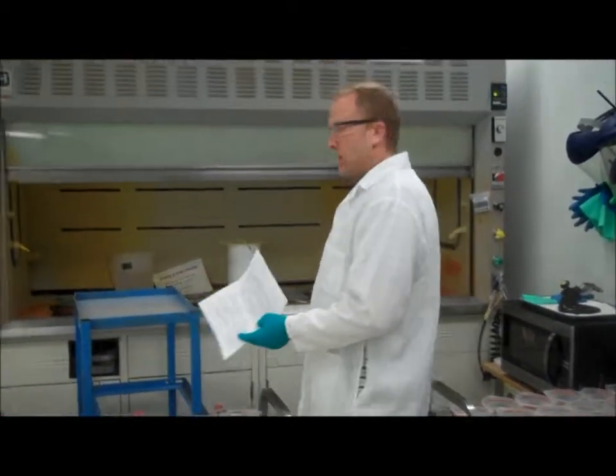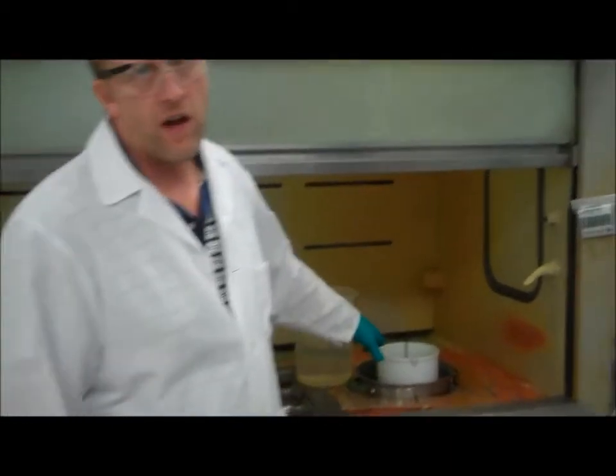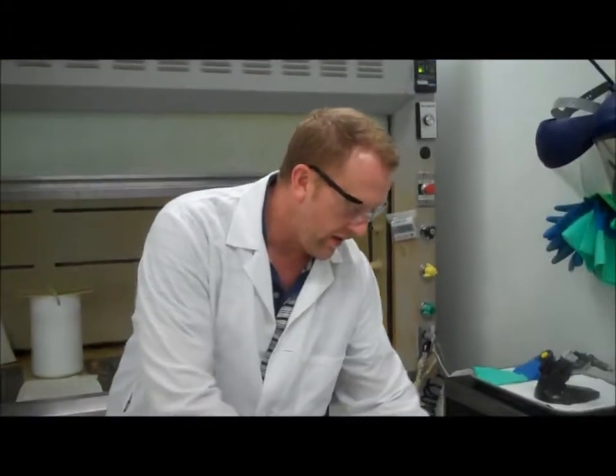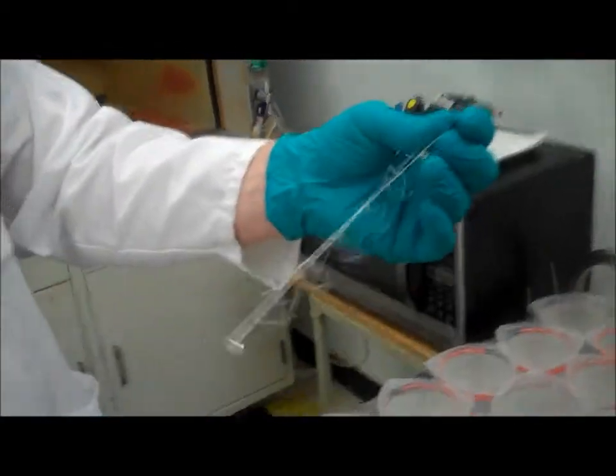The wire then goes into our acid etching station, which is a mixture of strong acids. Typically we try to remove all of the oxide in a certain amount of diameter to hit our target thickness that we're looking for from customer specifications. So after the wire is etched, you can see that most of the oxide is then removed. This preps the wire for our next step, which is going to be the electropolishing solution.